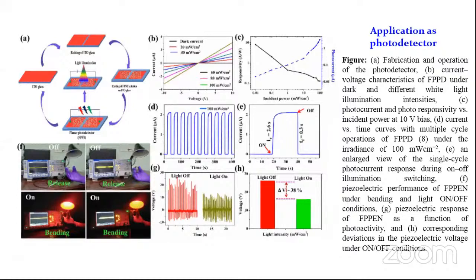Another interesting feature of the fabricated device is that it acts as a photo detector. For the fabrication of the photo detector, we have taken a patterned ITO glass. Then after forming a depletion layer, we have spin coated the PVDF and formamidinium lead bromide composite. After spin coating, it was dried in the oven. After that, we have measured the current and voltage of the photo detector. We have seen that with increasing intensity of the light, the voltage and current increase. Also, this is ohmic in nature.